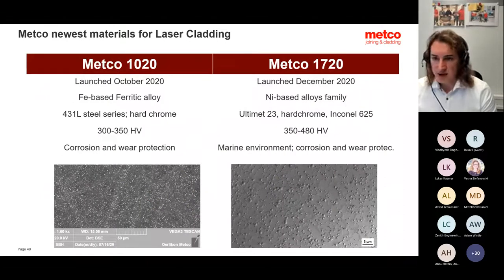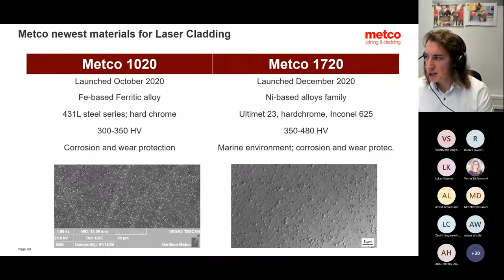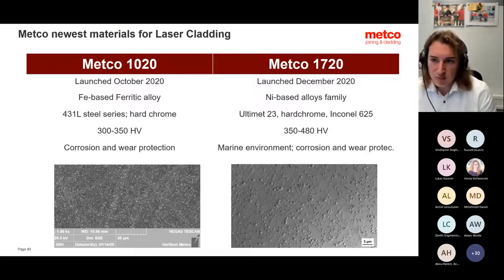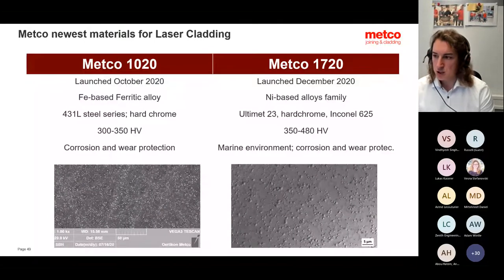That's how we, for example, have launched two of our products. One is an iron-based material, fully ferritic, in competition to 400 series martensitic stainless steels. And from another side, we simply made Metco 1720, which is nothing else than an Inconel 625 microstructure higher hardness alloy, which has the same salt spray results, but has high hardness values and outperforms even materials like Ultimet in terms of wear resistance and might be considered, for example, for marine environments and hydraulic rod applications.